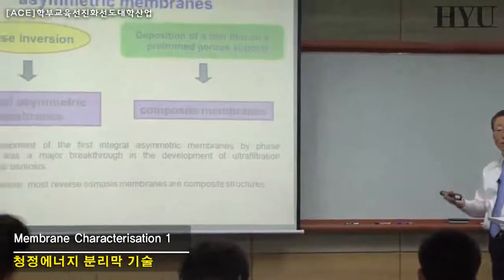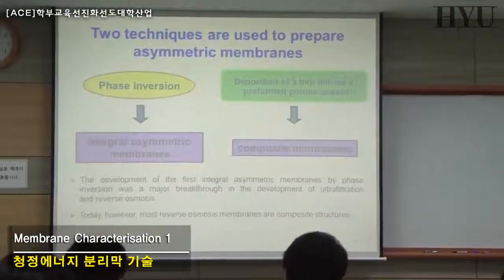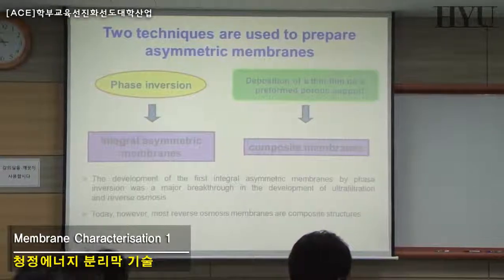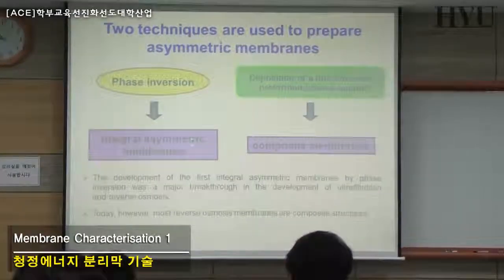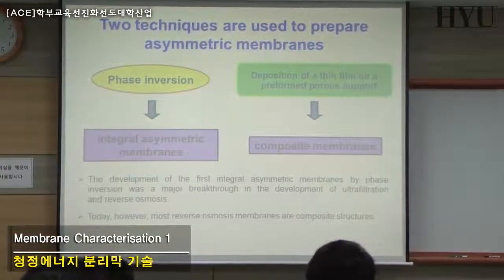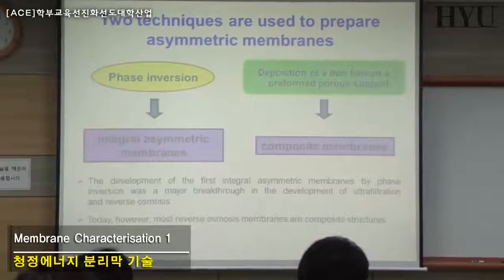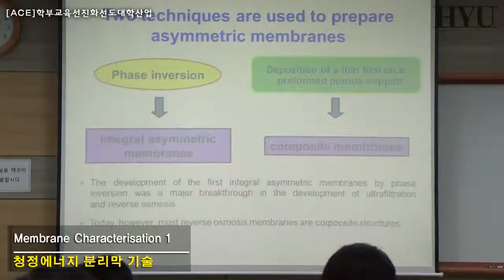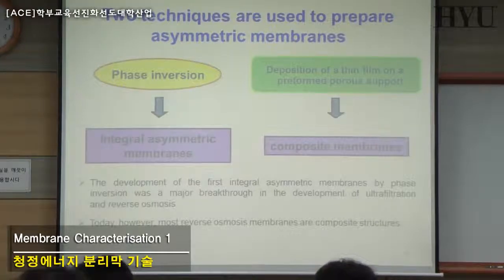So let's talk in more detail about how we can make an asymmetric membrane by using phase inversion or phase separation. By using the phase separation, phase inversion, we can make an asymmetric membrane from one polymer. Okay? I think we have given an example of cellulose acetate, the Loeb-Sourirajan type of integrally skinned membrane. That's what we call phase inversion. We can make a composite membrane mimicking this asymmetric structure. We have a porous support. If you coat a very thin layer made of a second polymer, then combine it together, that is what we call the composite membrane.